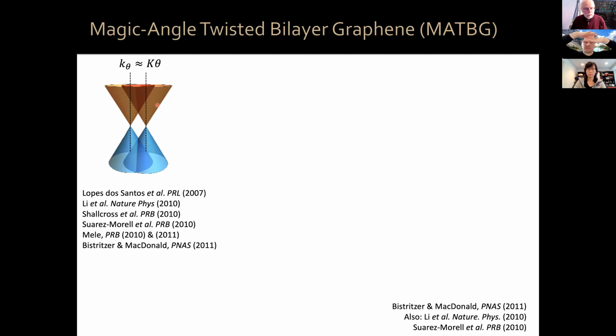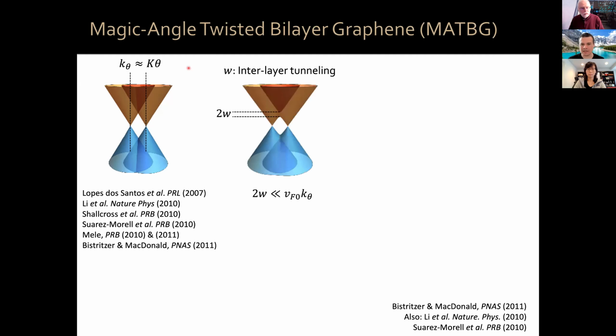However, because these two graphene sheets that we place on top of each other are only 3 angstroms apart, electrons can very much tunnel between the layers, okay? So that interlayer tunneling leads to bonding and anti-bonding states at this crossing point, okay? So you get one band which gets pushed down a little bit in energy, and the anti-bonding band gets pushed up in energy, okay? This is exactly the same as bonding and anti-bonding states in a hydrogen molecule, but now with 2 giant graphene sheets. So it's a giant graphene molecule if you want, yeah?